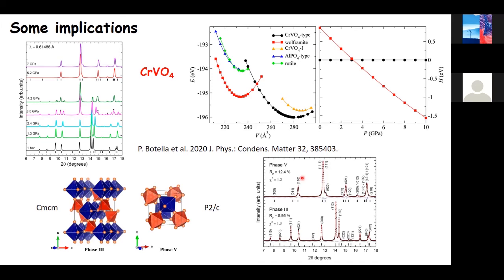So clearly there is a systematic of many compounds crystallizing in this orthorhombic structure and, under compression at relatively low pressure, going to a lower symmetry monoclinic structure, which is a wolframite structure. You can see here at 3.5 GPa, you have the start of the transition. You have here the two phases coexisting, and you have here the high pressure phase.